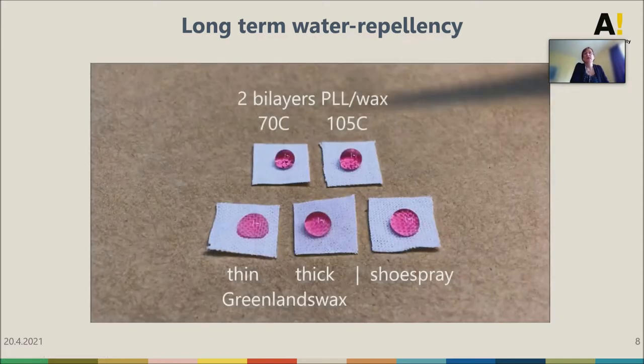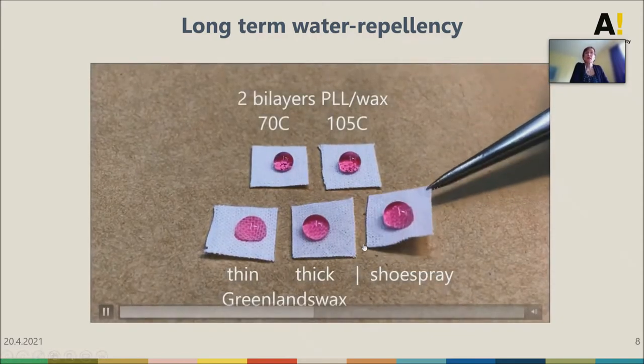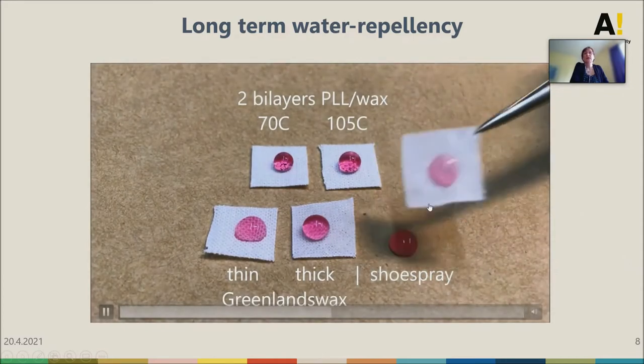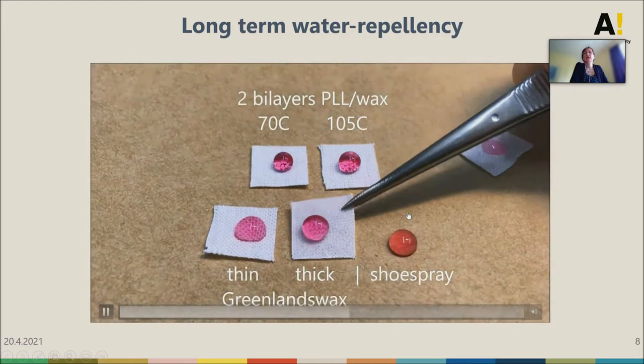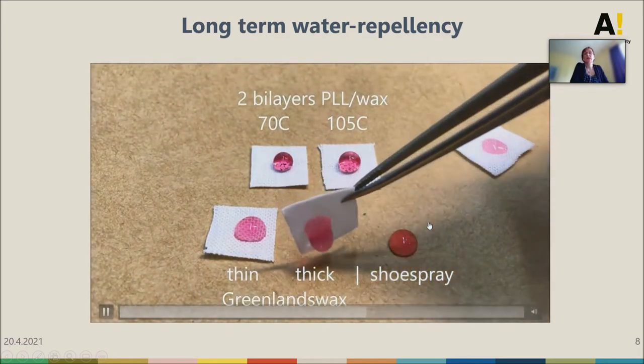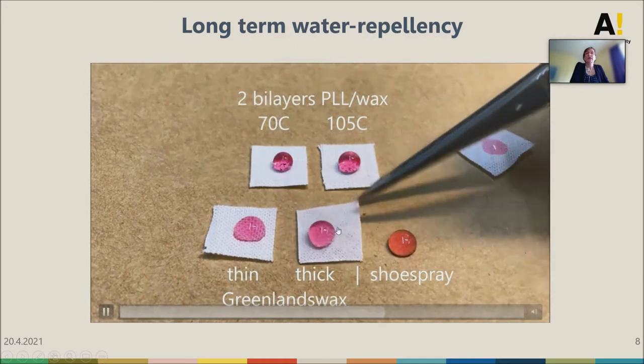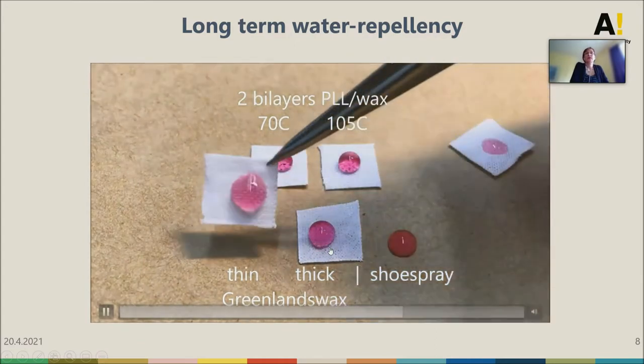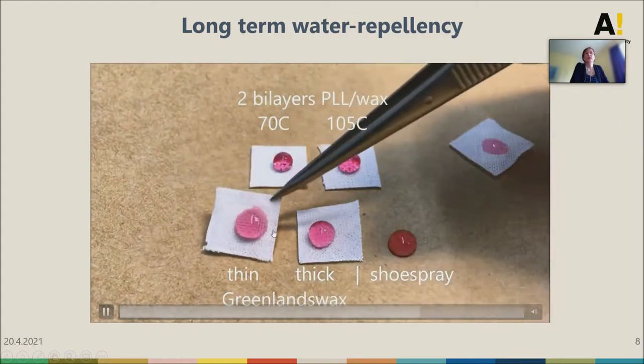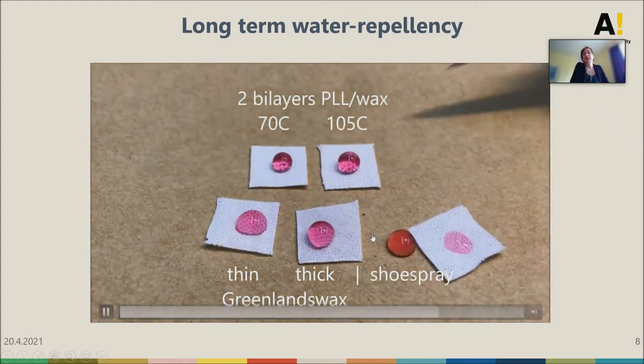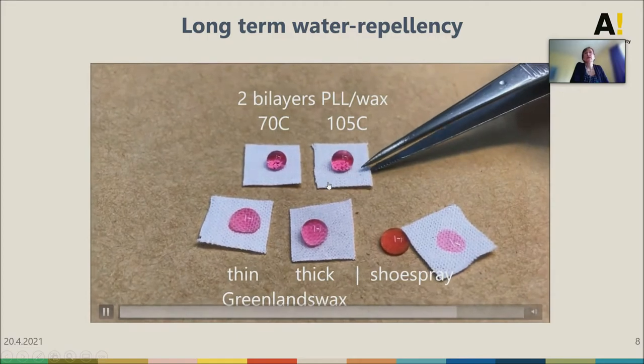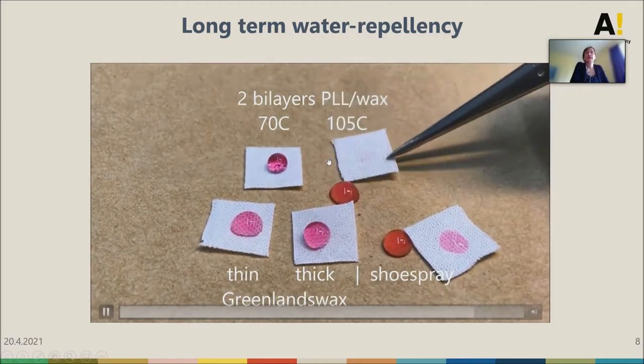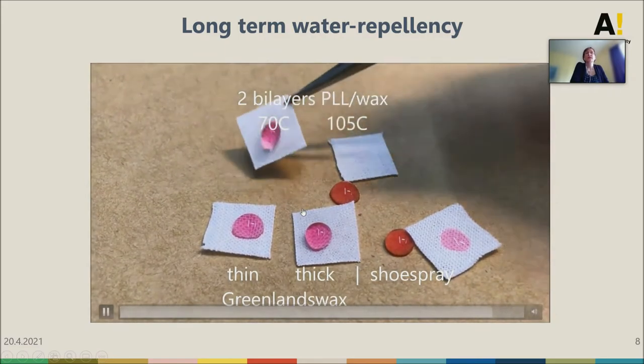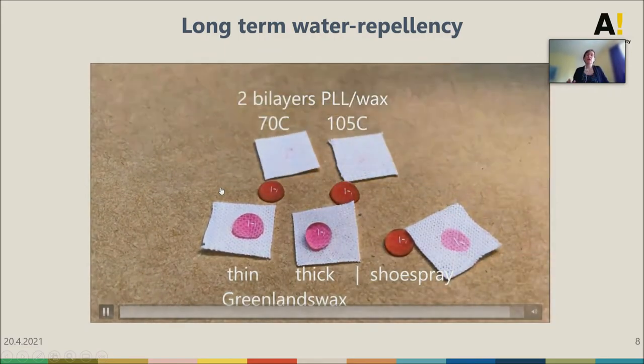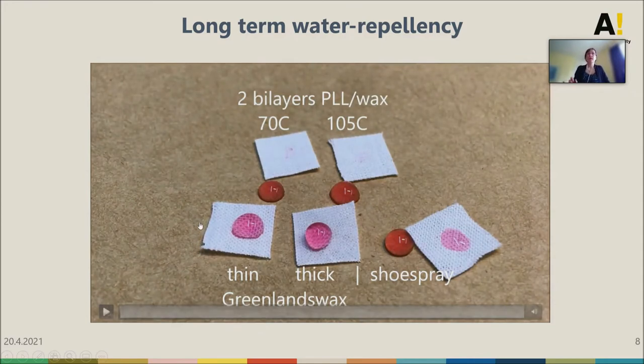So 20 minutes after this, we can see that these are a bit sticky. So the water stays there, and you can see that it's still left wet afterwards. So even if it looks like the droplet is hydrophobic, it's not so nicely hydrophobic. While with our system, the water can be easily removed and it's almost dry afterwards. So this means that, for example, this could be quite efficient to protect against rain or something.